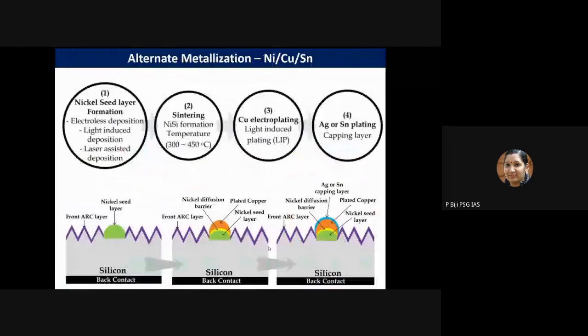If you see the alternative metallization, like nickel copper contacts, in the previous slide I have used silver, but you need not consider silver. If you are going for a silver-less process, the purpose of silver or tin in this case is only as a capping layer. That will prevent the oxidation of the copper and protects the metallic fingers. That's the purpose of using the capping layer.